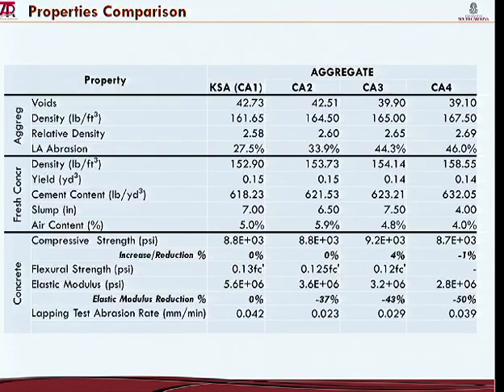aggregate. Now, when we look at the Lapping test abrasion rate, please note that the weathered aggregate showed a better performance than the standard aggregates. So basically, the lower this number, the higher the abrasion resistance. This number is the loss of material per minute of testing the samples, and I'm not going to go into the details at this point. But this finding contradicts the